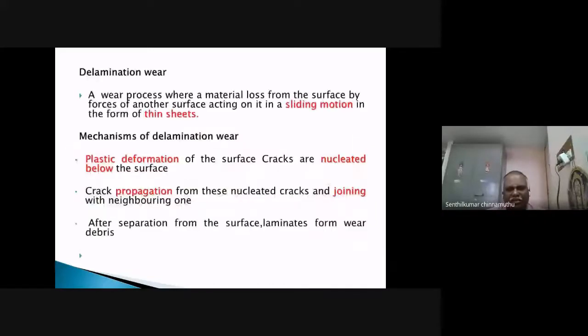Delamination wear. The wear process where the material is lost from the surface by the force of another surface acting in a sliding motion in the form of thin sheets. The material removed in the form of flakes or thin sheets is called delamination wear. How does it occur? Due to plastic deformation, subsurface cracks are nucleated below the surface. Due to the movement of the two mating parts, the crack is nucleated. The crack propagates from this nucleated site, joining with the neighboring one, and after separation from the surface, the laminates form a wear debris.